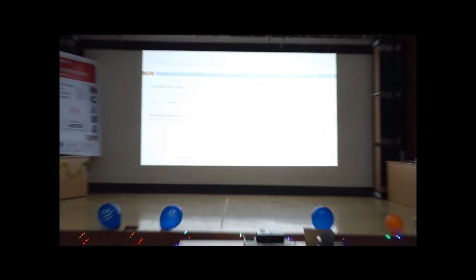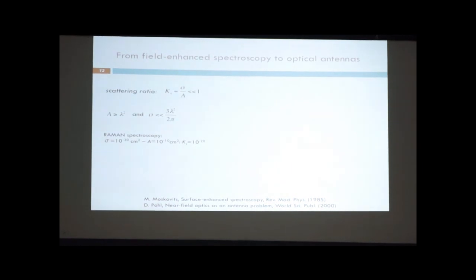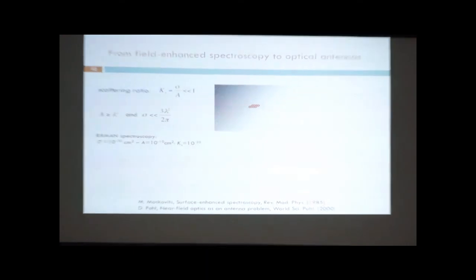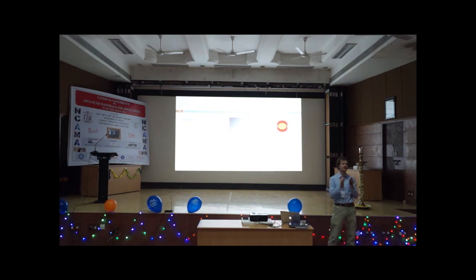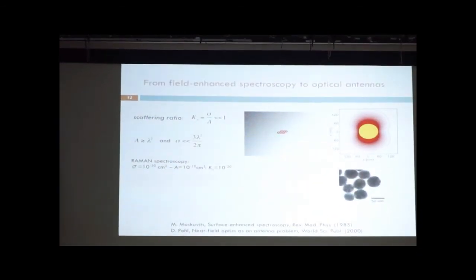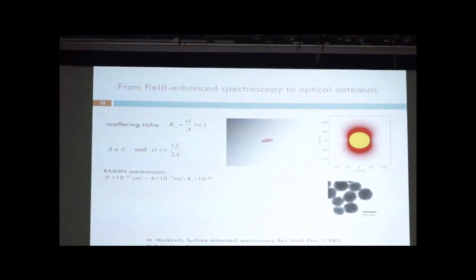So let me give you an example. And this is related to applications that have already been shown to work today: Raman spectroscopy. In Raman spectroscopy, you have to face a very small interaction strength, of the order of 10 to the minus 20 for a single molecule. And about 30 years ago, the spectroscopists understood that if you put the molecule on a rough metal surface, the signal is actually larger by orders of magnitude. And to understand this, they started to model this roughness as small metal islands. And they understood that these small metal islands could actually give rise to strong electromagnetic fields locally. And these strong electromagnetic fields could be engineered to some extent to increase this coupling. And then, with the ability to make nanostructures, they started to do experiments where people work with metal nanoparticles.